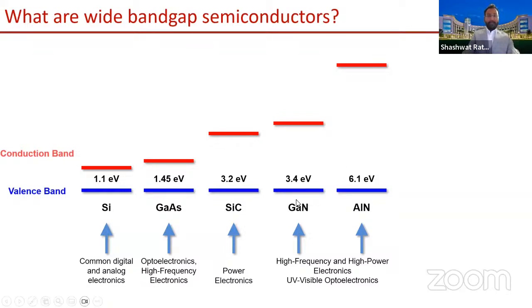For many years, these semiconductors were deemed as insulators, but not until lately, where people have been able to dope these semiconductors. And I specifically work on the highlighted region here, which is gallium nitride and aluminum nitride. We call these materials group 3 nitrides because you have group 3 metals, gallium and aluminum, and you have nitrides of these metals. The tight binding of these elements leads to a wide band gap in these materials, and as we'll see later, this wide band gap makes these materials exceptionally useful for high frequency, high power electronics and UV visible optoelectronics.